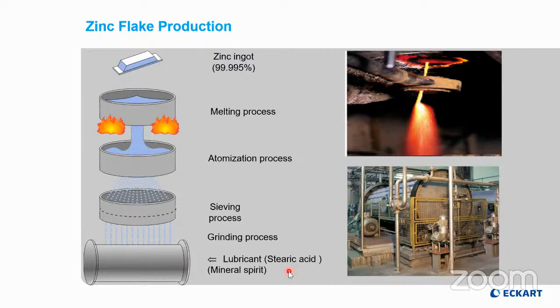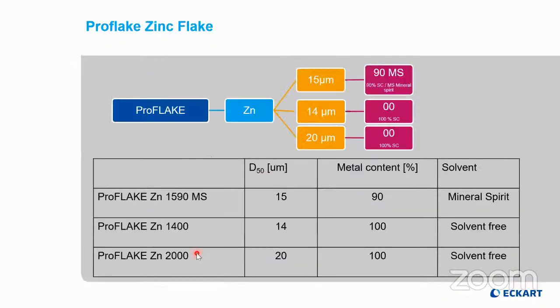This is done using a lubricant, stearic acid, in order to avoid cold welding during the milling process. The milling is predominantly done in a dry milling process, but it can also be done in mineral spirit. Both options are possible and are done in our factory. The current ProFlake zinc flake portfolio is relatively limited, yet sufficient to fulfill all the requirements. We have 2 zinc flake products in powder form with 2 different average particle sizes: a finer one, 14 micron, ProFlake 1400, and a coarser one, 20 microns, which is the standard pigment where we initially start to work.